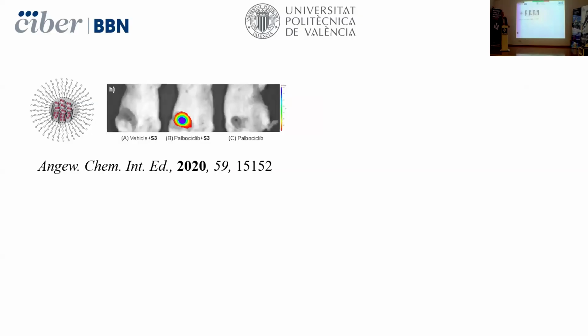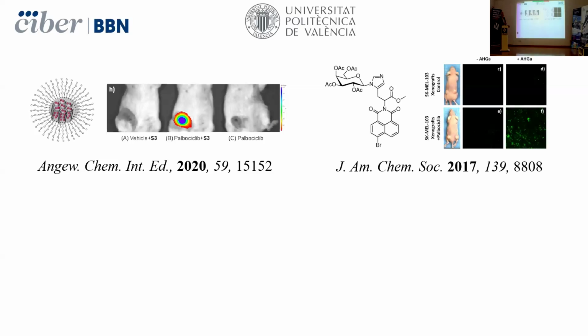Well, we can also use nanoparticles for detecting senescent cells. So this is a similar nanoparticle as we have seen before, but it's not loaded with doxorubicin, it's loaded with a dye. So the idea is that when the nanoparticle arrives, in that case, at tumors that are senescent, the dye is released and that can be monitored in vivo. We are also very much interested in developing probes. This is another example for the detection of senescent cells, but it's based not on nanoparticles, but on molecular probes. So this is a 2-photon structure that allows detection of senescent cells in a model of melanoma ex vivo.